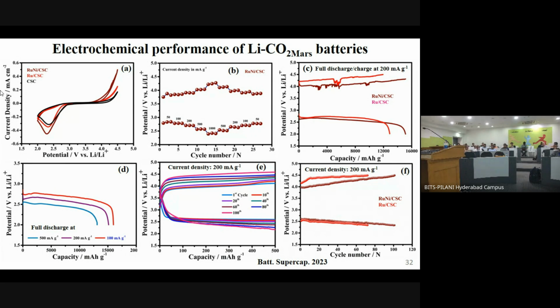And with respect to the different systems, this is at different current densities, we see the overpotential value and also the full discharge value. So when we fully discharge, wanting to use it as a primary battery, we can really go up to nearly 15,800 milliampere hour per gram, which is way higher than reported values in the literature. Similarly for different cycles, here, for the first time, we were able to cross 100 cycles of charge and discharge with the help of this ruthenium nickel on the candle soot carbon.